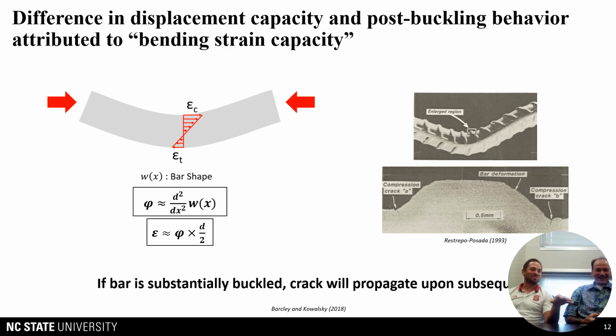Chad did a bunch of those tests, so it was a direct comparison between Grade 60 and Grade 80. And I think when we were thinking about it, Chad developed a bunch of different equations for where the cage or the spirals yield, and then what yields to then bar buckling, in terms of trying to get different limit states. And bar buckling was always, you kind of bar buckles, and that's where you design to, and then you have a little bit of factor of safety after that. But after seeing it, you don't really have a whole lot of factor of safety after bar buckling with the Grade 80 column.